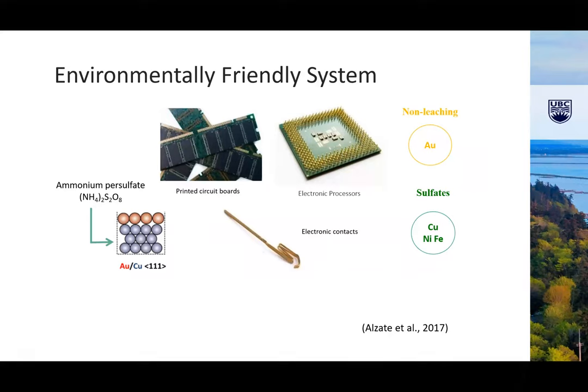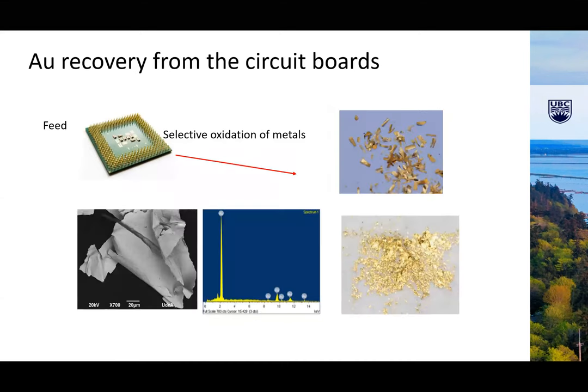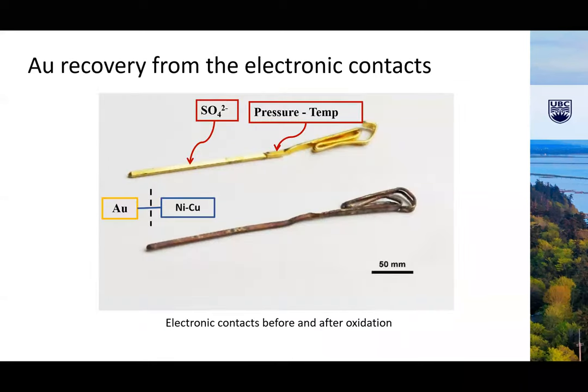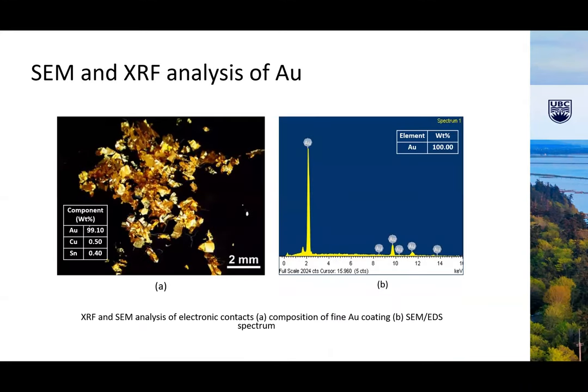And after that, the gold was released, and the temperature was less than 100 degrees. I think it was about 95 degrees of the solution. So the feed, selective oxidation of metals, led to the release of gold. And it was quite amazing that it could have been done as simply as that.